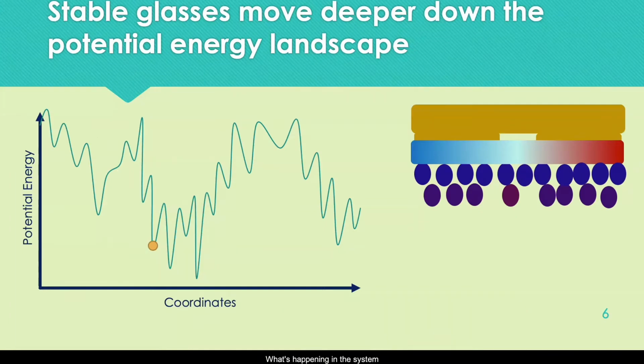So what's happening in this system is, again, that we have enhanced mobility at the surface. The most recently deposited molecules have more room to move and therefore have an enhanced mobility. So the system is able to overcome barriers and sample a number of configurations in the potential energy landscape to try and find a more stable state.